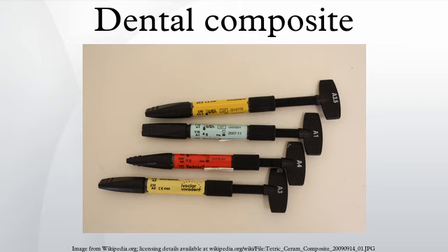The enamel margin of a composite resin preparation should be beveled in order to improve aesthetics and expose the ends of the enamel rods for acid attack. The correct technique of enamel etching prior to placement of a composite resin restoration includes etching with 30%–50% phosphoric acid and rinsing thoroughly with water and drying with air only. In preparing a cavity for restoration with composite resin combined with an acid etch technique, all enamel cavo surface angles should be obtuse angles. Contraindications for composite include varnish and zinc oxide eugenol.